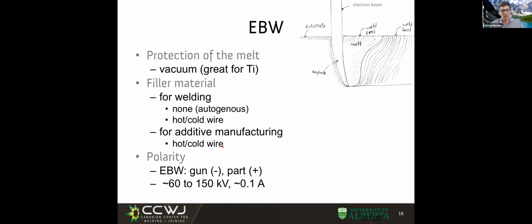Now, electron beam does not look at all like arc welding, but it has a similarity. We have an electrical current, but while in arc welding we have relatively low voltages, more or less 15 to 35 volts, from 10 volts in a little TIG to a huge submerged arc welding system, and the currents are high, 100 or 200 amps for a little arc weld, 1000 amps for a heavy submerged arc weld. Electron beam is the opposite.